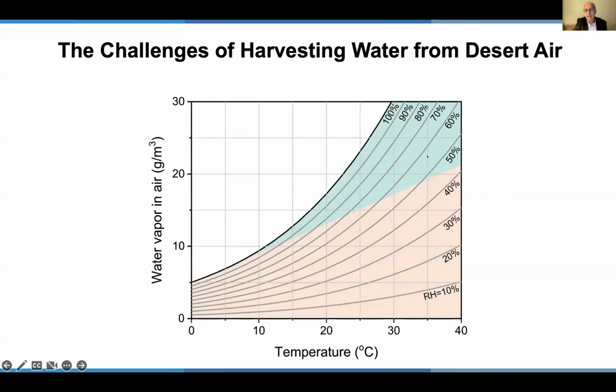The green area is where the world is hydrated or there's high humidity, and the brown area is where the humidity is low. So this is a psychrometric chart. I'm plotting on one side grams of water in the air per cubic meter of air, and on the other side, the temperature. So let's imagine that I'm in a Mediterranean city, where the temperature might be 30 degrees Celsius and the relative humidity 20%. Let's imagine I want to take that water out of the air there. To do that, I must cool that air down to 4 degrees Celsius, which makes it extremely uneconomical.